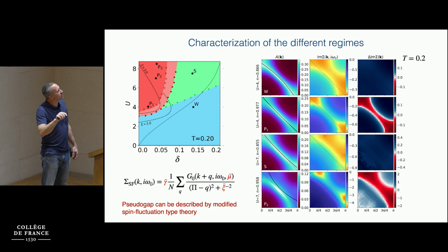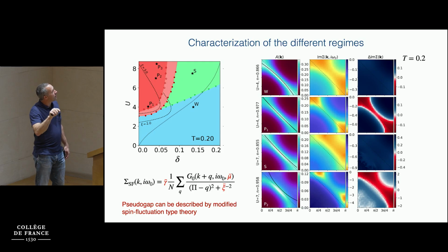If I go to the strongly correlated metal, this line, again, no pseudogap at this point. The self-energy starts to be a bit stronger, strong enough to deform the Fermi surface, which now, if I track the maximum, has become hole-like. In the pseudogap, we start seeing places where the self-energy slope has changed. Quite in general, the self-energy has become much bigger and starts displaying pole-like structures just above the antiferromagnetic Brillouin zone, here close to pi, 0, both in the weak coupling and also in the strong coupling.